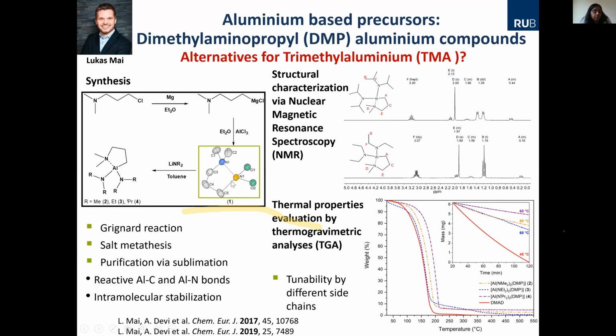You see single crystal X-ray diffraction shows the metal atom and the surrounding ligands, and we use different synthetic routes and see the NMR, whether the molecule is formed, the spectroscopic purity, and most important is the thermal properties, as I said in the beginning, whether the precursor will volatilize or evaporate or sublime as a function of temperature. Because in a CVD process or ALD process, you have to bring it in the gas phase.